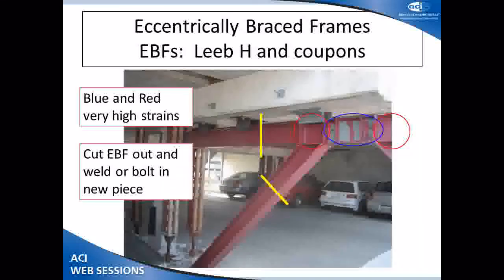These zones were measured using Leeb hardness tests and water jet cut coupons, not heat cut coupons. And we found that the strains there were right at the end of life in those particular elements. We also found that the high strains actually worked out along the header and down the legs as well. The solution was to cut those pieces out and replace them in their entirety over the building.